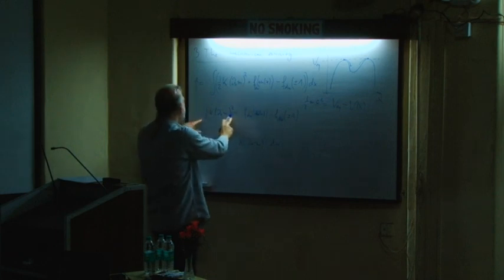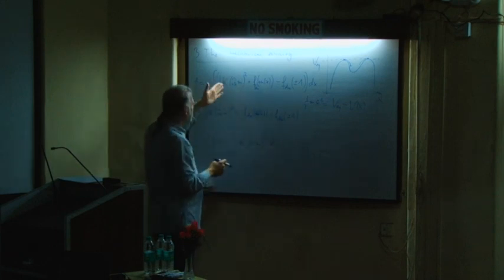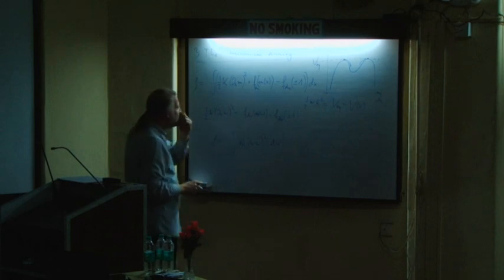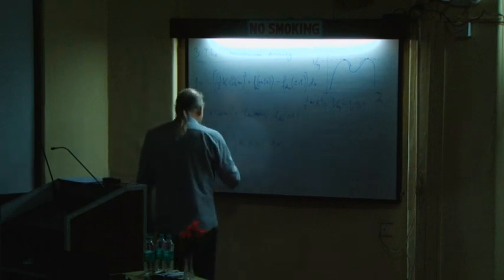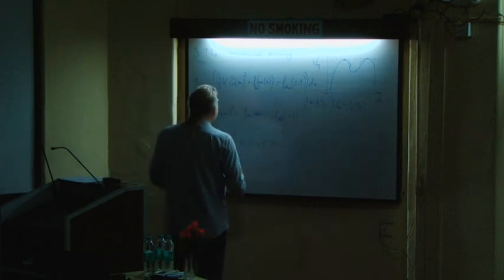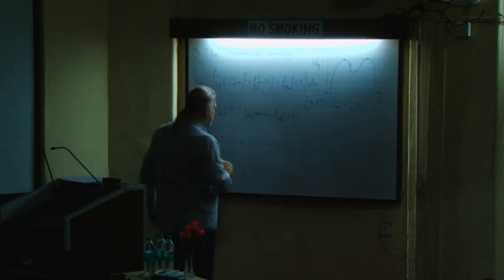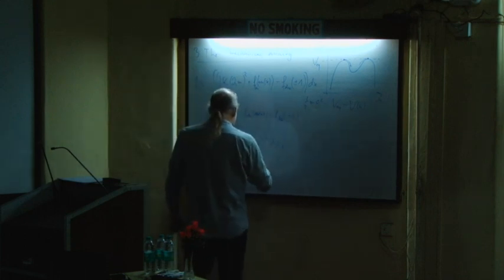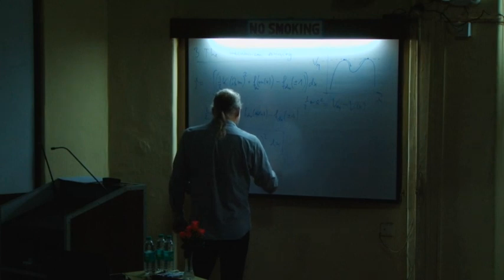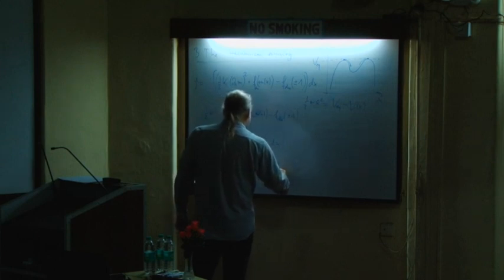So you see there's 2 times 1/2 k gradient squared, so you just complete the gradient term. And then there is a second one, which is the integral. And now if I replace the gradient term, I just get 2 f of m minus f of plus or minus 1.